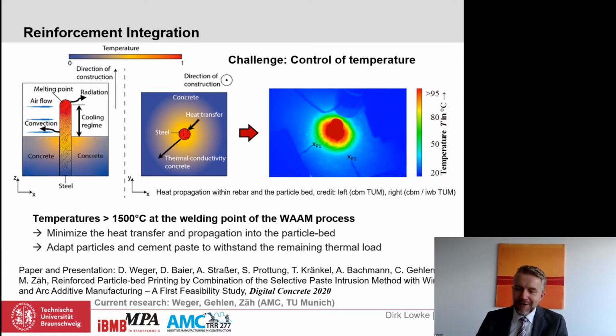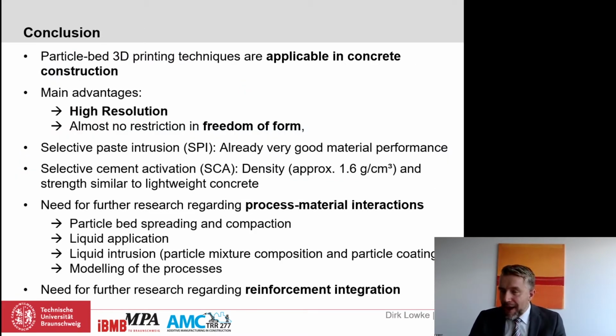Let me now conclude my talk. I believe particle bed 3D printing techniques are applicable in concrete construction. The main advantages of these techniques are their high resolution and the fact that they have almost no restriction in free form and the freedom of form. For the selective paste intrusion technique, we already have very good material performance. In the case of selective cement activation, the density is about 1.6 gram per cubic centimeter, and therefore the strength is similar to lightweight concrete.